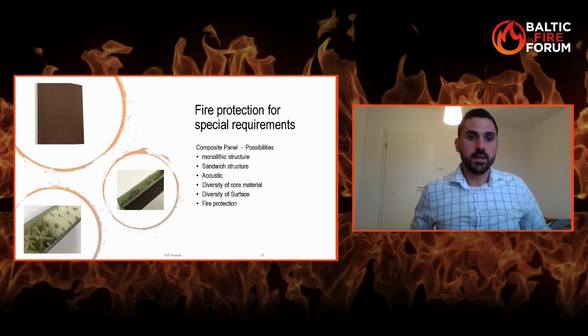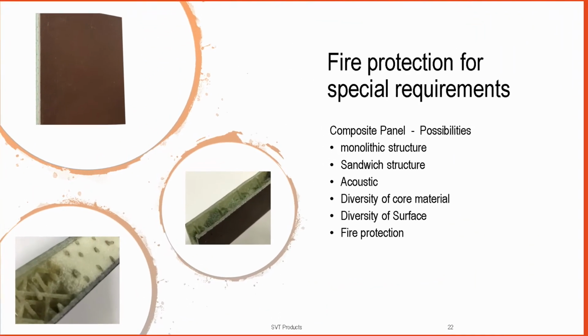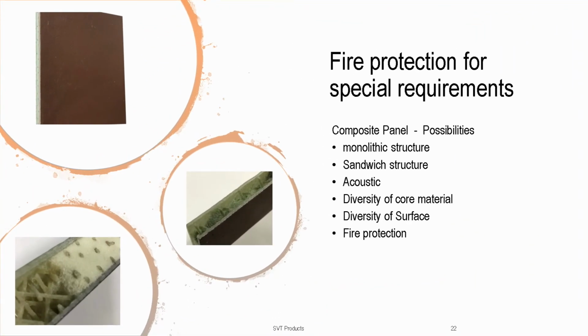There. So here you can see some pictures. As I already told you, we have some possibilities for this material. We can build it in a monolithic structure. It's only the fiber with the fire protection coating and some epoxy resin, and you get a small inlay, about 1 to 2.5 millimeters thick, that you can use. But it's already possible to build the whole battery box or the whole transportation case, or everything you want to build with this kind of material.